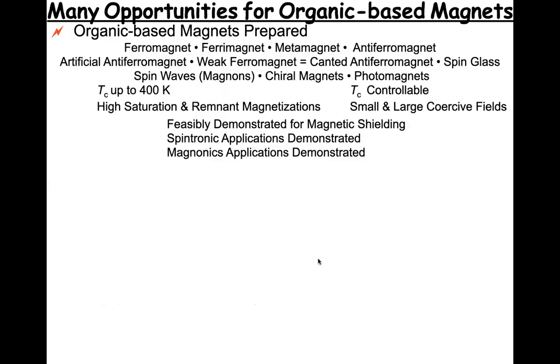So to summarize, organic-based magnets, we can make ferromagnets, ferrimagnets, metamagnets, antiferromagnets, artificial antiferromagnets, weak ferromagnets, which are canted antiferromagnets, spin glasses. We have demonstrated applications with spin waves, magnons. Other people have made chiral magnets and photomagnets. We have ordering temperatures up to 400 Kelvin, and we can control that.